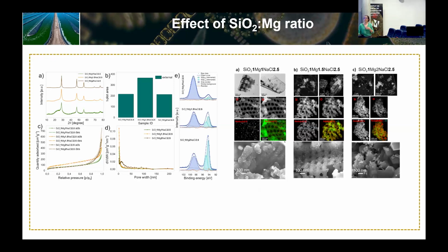But when we go to the 1:2, so there are more reactions and more heat is produced, then these small silicon crystals start to grow a lot, and then the nanostructure collapses, and we have huge silicon crystals in there. So this means that we have to be more careful and fine-tune the amount of sodium chloride when we increase the amount of magnesium in the sample.